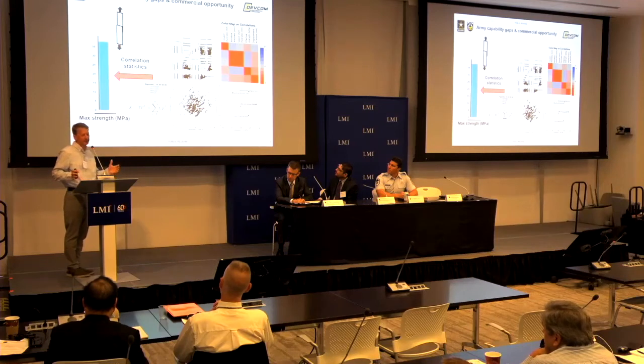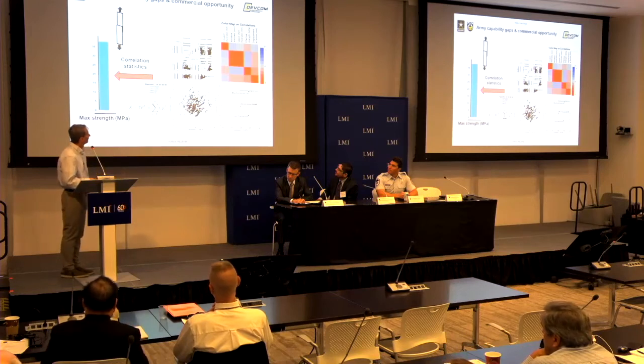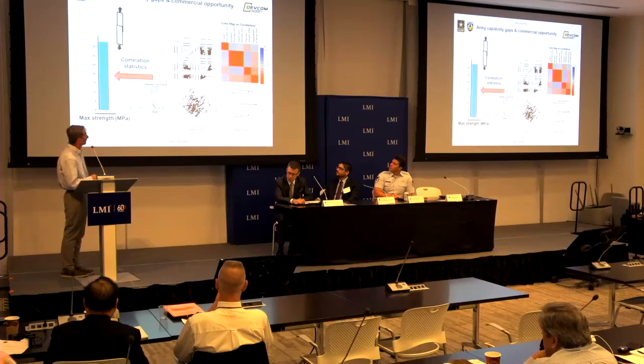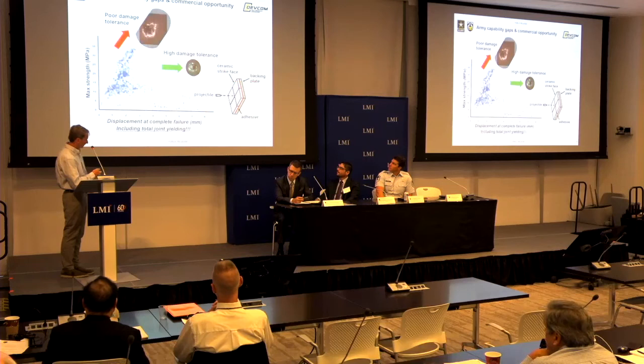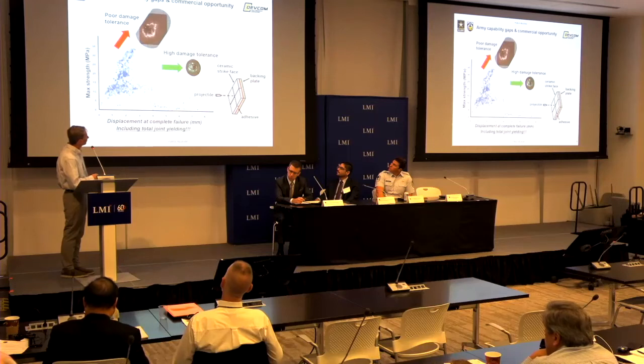We shifted the adhesives team over to running on a database on a materials informatics platform to capture data faster. So we had all this data on adhesives, thousands of adhesive data points on a few hundred adhesives, and then basically what we were able to do was rigorous multivariate statistical analysis to get the correlation maps and correlation statistics to our friend the single lap shear joint, which is the industry benchmark. And then we found out when we took maximum strength and incorporated displacement and complete failure, lo and behold, we got a correlation to armor performance.